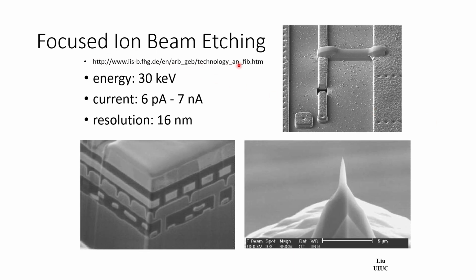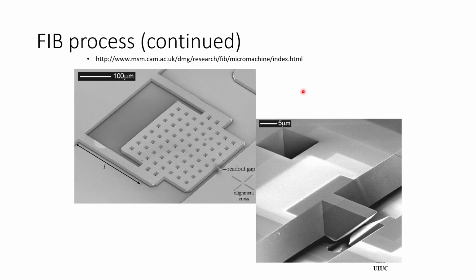Focus ion beam etching is another type of process where it's like an ion beam formed in a scanning electron microscope. You can use this to carve out cross-section structures or break structures such as metal wires, or use growths to form very sharp needles out of carbon conductive materials. The focus ion beam etching can also be used to etch sideways. For example, in this case, you can form capacitors that can measure the displacement of a proof mass that is suspended by two beams.